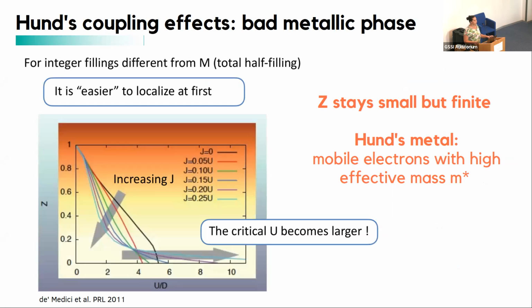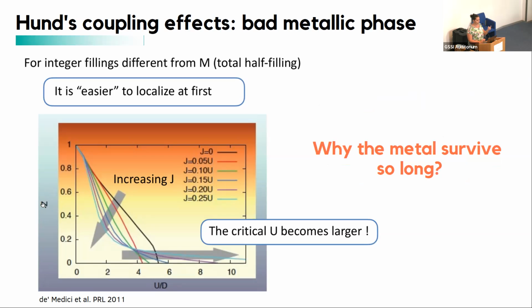It could change with doping, but it's pretty robust that for any integer filling, imagine that I have 5 orbitals, for 1, 2, 3, 4, except half filling, so 1, 2, 3, 4 electrons in 5 orbitals, I have the same physics. This is the plot of the quasi-particle weight, so the coherence, the reduction of the kinetic energy, with increasing U. I'm plotting different colors with different J values. You see that essentially J has 2 different effects.